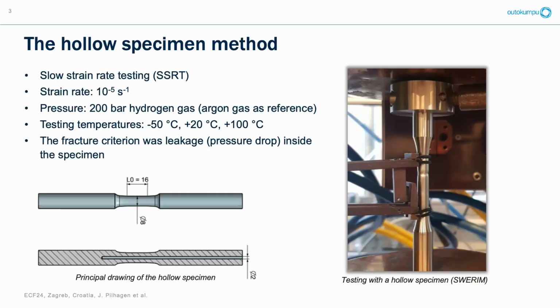And the main benefit of this testing method compared to an autoclave is that you have a lower cost. You don't need to invest in an autoclave, and you have lower hydrogen consumption. And you can also easily instrument your specimen, not only with strain gauges or extensometer, but you can also apply fluoroscope, acoustics, or if you want to put it in an X-ray or neutron source.